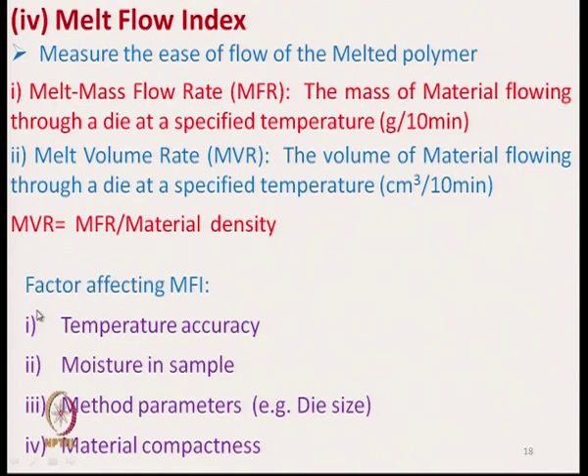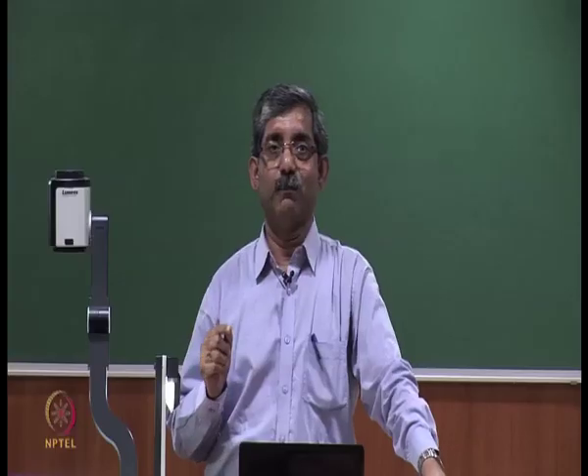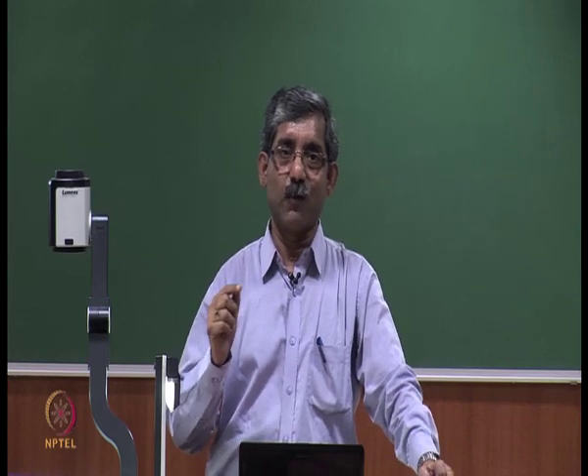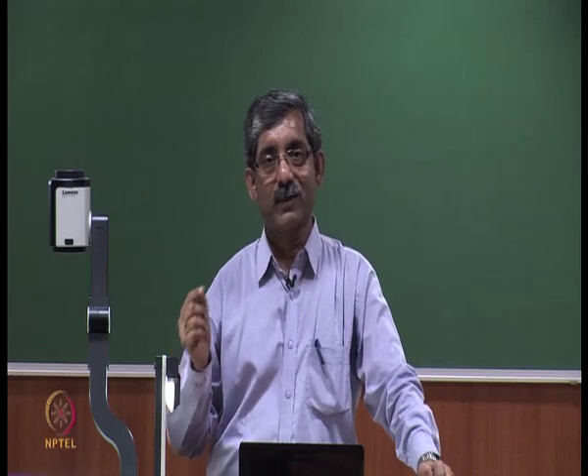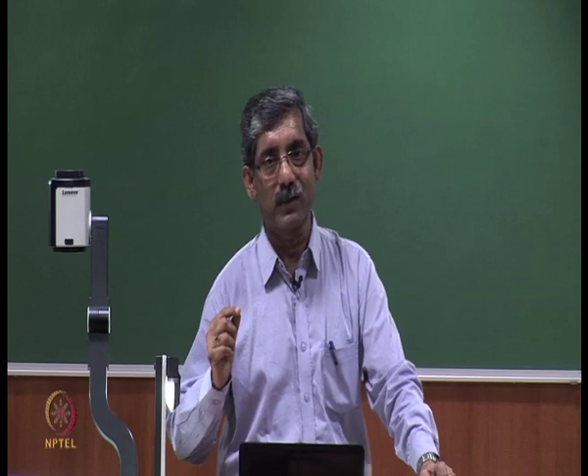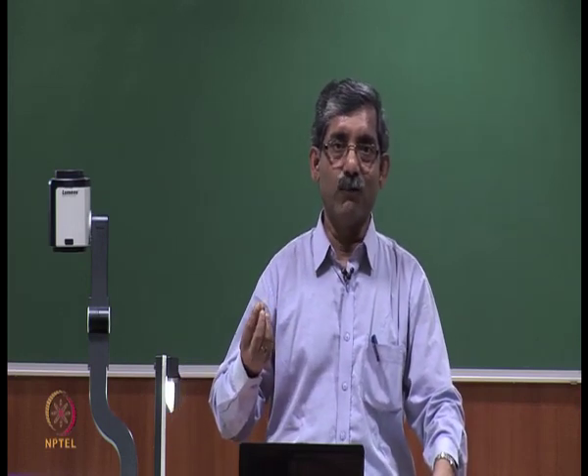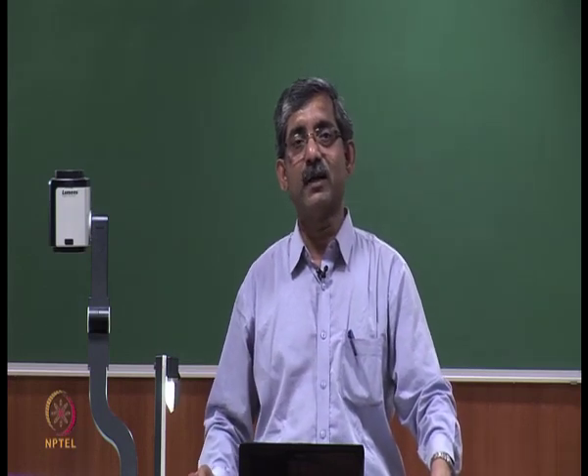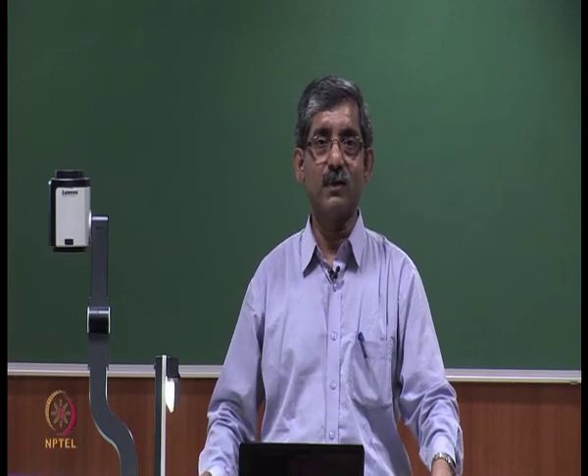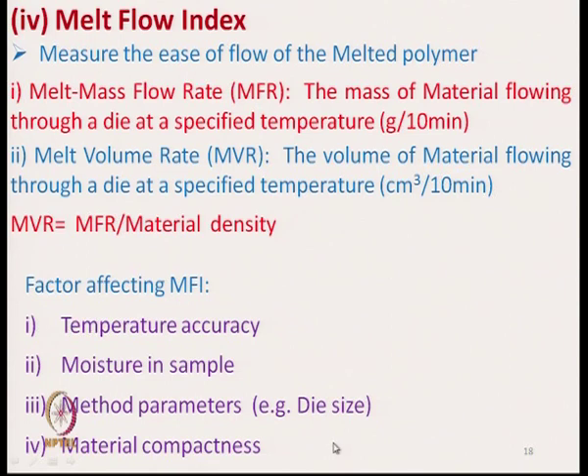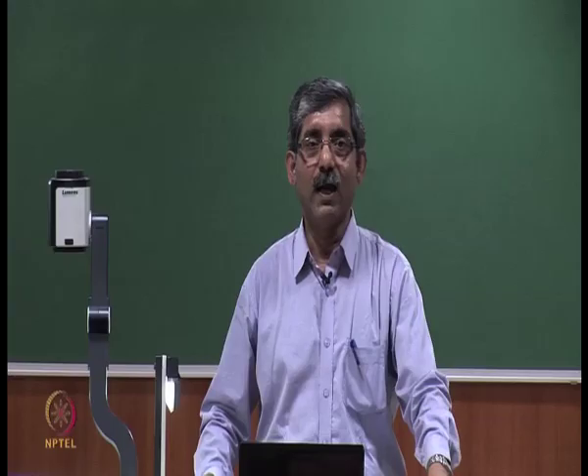The factors which affect the melt flow index are temperature accuracy. When we heat the material at a particular temperature, if the temperature accuracy is not maintained properly, with a sudden increase in temperature, even 1 degree, the melt flow index will change. So the temperature should be maintained perfectly, otherwise we will get a wrong result. Other factors are moisture in the sample and method parameters like die size.